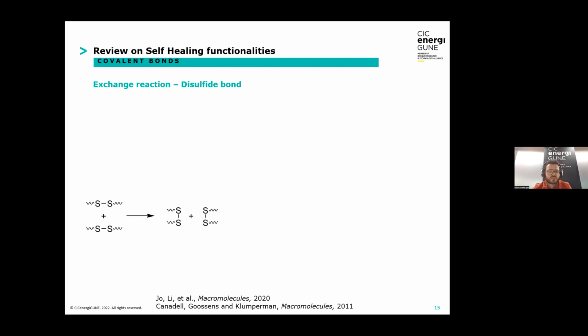There are different examples. So first, looking at the exchange reaction with these disulfide bonds, here in this exchange reaction, the self-healing moieties continuously exchange within the network, and this reversibility is due to the low energy required for these bonds compared to other covalent bonds bonding self-healing techniques. The energy required is still 6 times higher than that for non-covalent bonds, which we approximately said it is 10 kilocalories per mole. Therefore, this is considered kind of an intermediate step between the energy required for non-covalent bonding and for high energy demanding or consuming covalent bonds for self-healing.